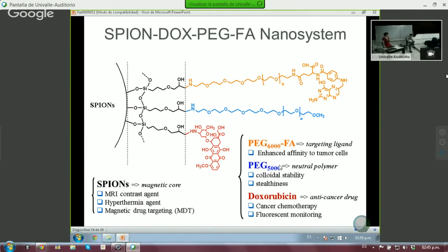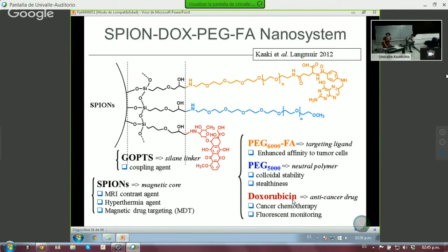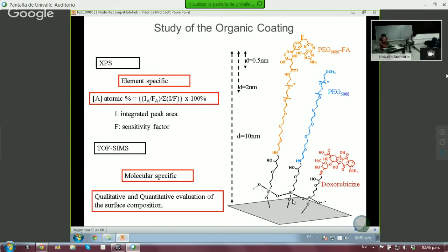And in a way, it helps in maintaining the colloidal stability of these nanoparticles so they don't grow by touching each other and getting together, and also helps the stealthiness. And the drug we used is doxorubicin, so we had to hide it inside. This is a cancer chemotherapy drug, and it helps in fluorescent monitoring. And this gives you an idea of the synthesis which was carried out. Then we came up with our samples, with the drug designed to be very well camouflaged and so on. But we need again to investigate if this is the case.